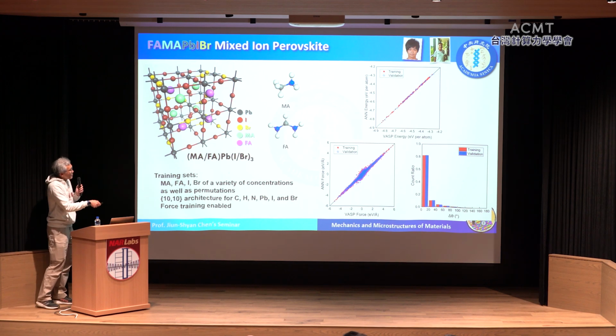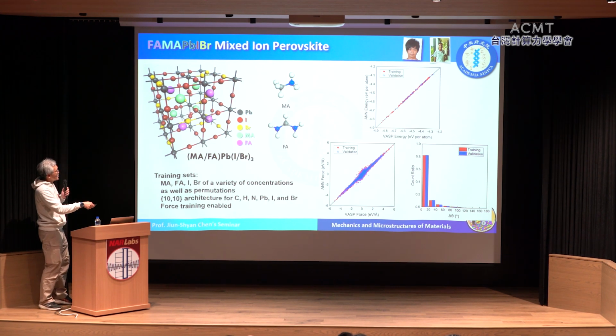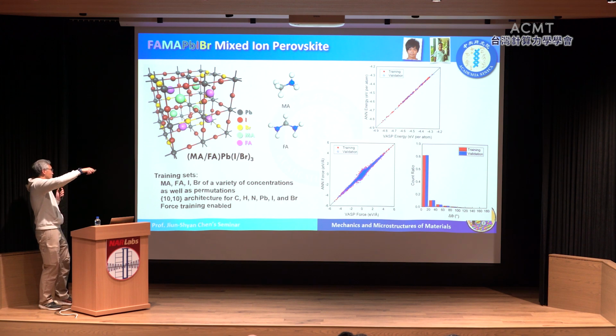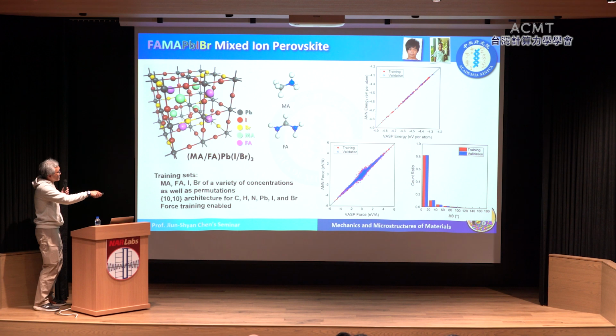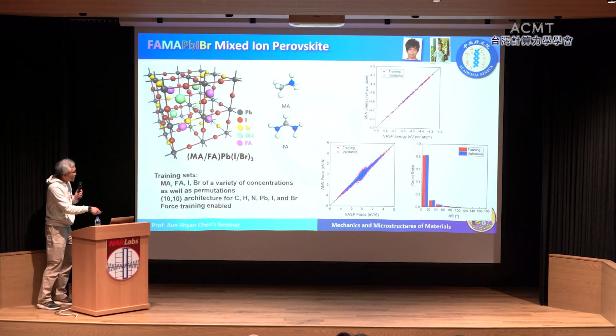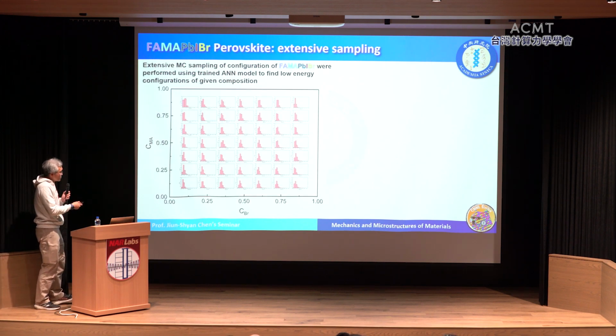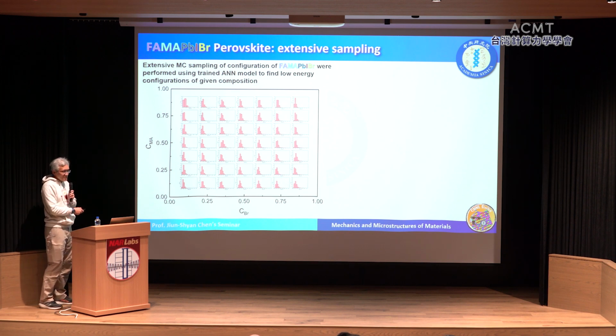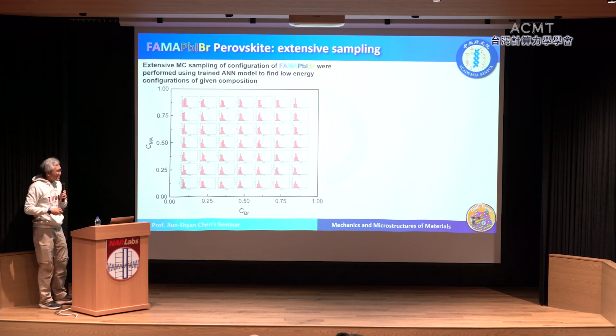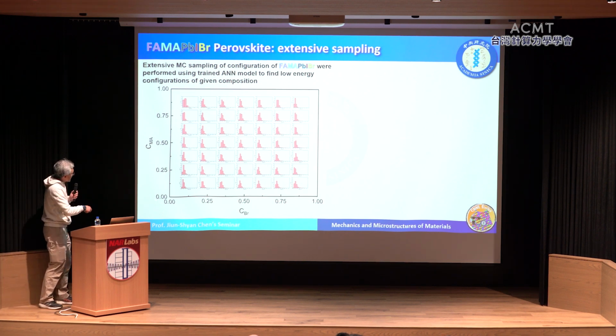So you can see that by using a neural network, we can train an energy model. The horizontal axis shows the ground truth from VASP calculation, and the vertical axis shows the prediction from the neural network. And you can see that the parity is pretty good. We can also have a very good parity for atomic forces. Because this is much faster than the DFT calculation, and it's almost as accurate, we can use that to do extensive sampling over the compositional space.